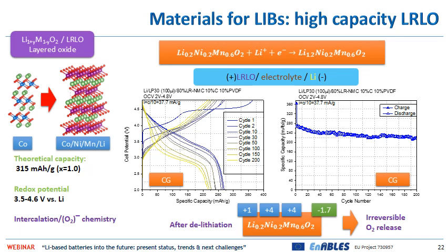However, there's always an however. When we fully deintercalate this material, if we have a look, for example, at the most common stoichiometry for this family of materials, that is lithium 1.2, nickel 0.2, manganese 0.6 O2, the fully deintercalated material has a stoichiometry in which, after the delithiation, the formal oxidation number of lithium is +1, of nickel is +4, manganese is +4, and oxygen is unavoidably -1.7. This means that this reactivity is not a full intercalation reaction, but has also some oxide-peroxide chemistry that is occurring.